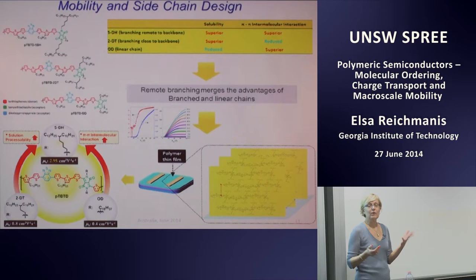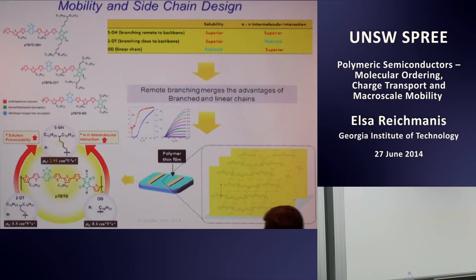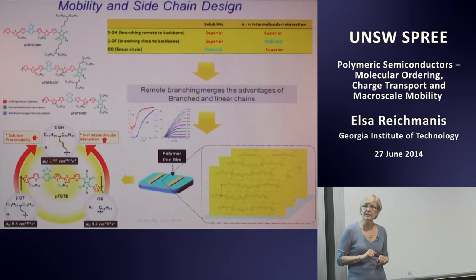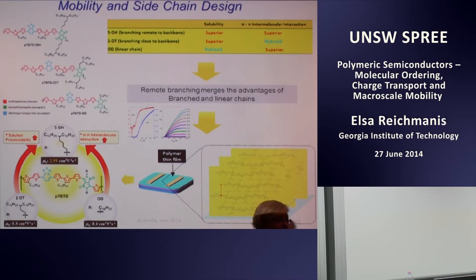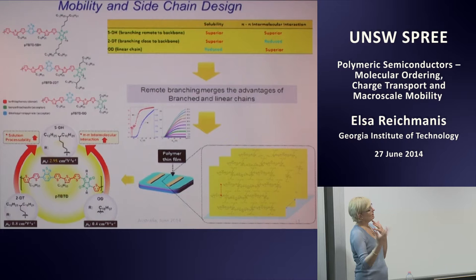Having the branching point near the backbone improves the solubility. That actually allows a higher molecular weight polymer to be formed, and the maximum mobility that we may be able to achieve in that polymer goes up to 0.8 centimeters squared per volt second. Also reasonably good.